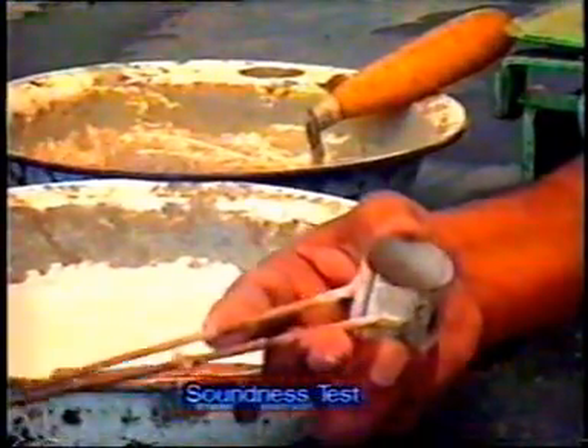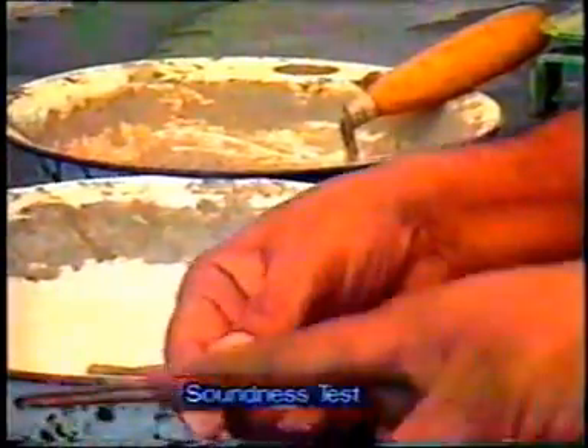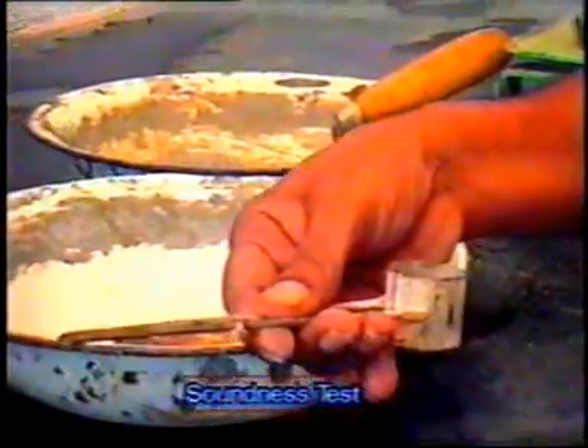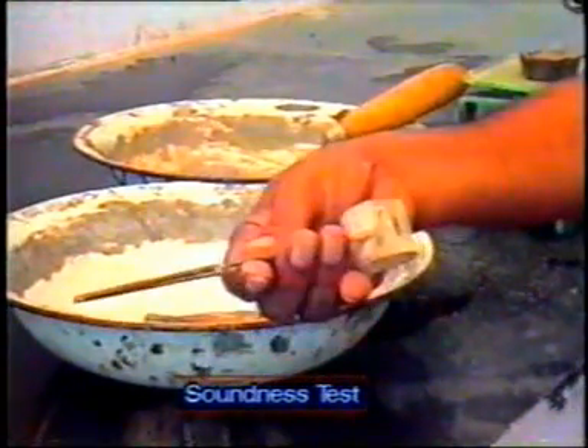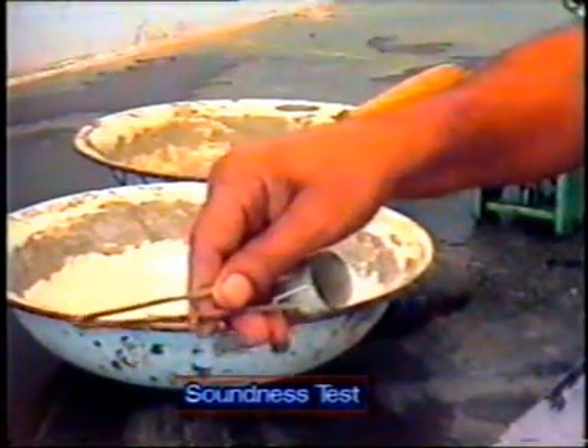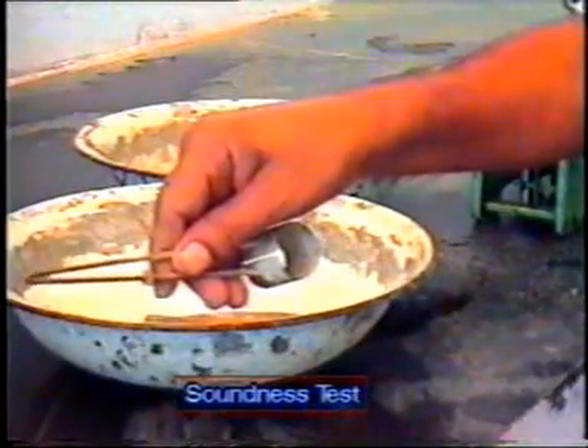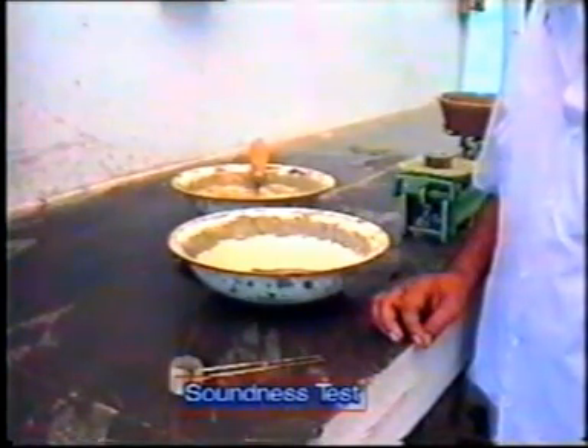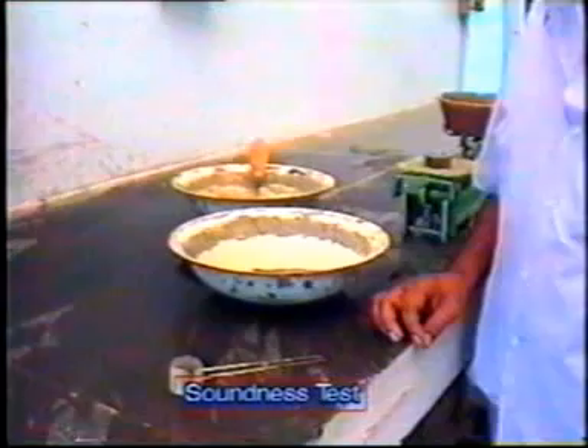This unsoundness is due to the presence of excess of lime than that could be combined with acidic oxide at the kiln. It is also due to insufficiency in fineness of grinding, too high proportion of magnesium content, etc. Now, let us see the apparatus required for the soundness test of the cement. This method is by the Le Chatelier's apparatus.